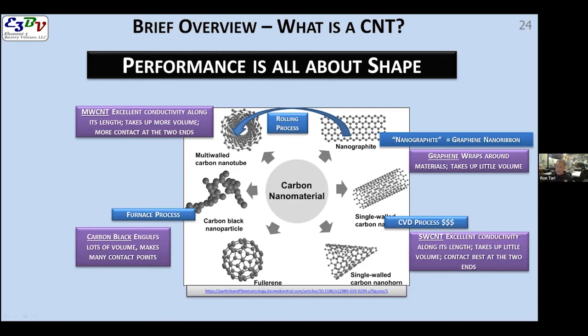A single wall carbon nanotube is probably the most effective thing if the diameter of this tube is less than 10 nanometer, and there are such things out there. If it's much larger, then it probably won't be a whole lot better than some of these multi-wall nanotubes that are made through the rolling process. All of these are available, by the way, and they're used not just in anodes, they're used in cathodes to extend battery life.